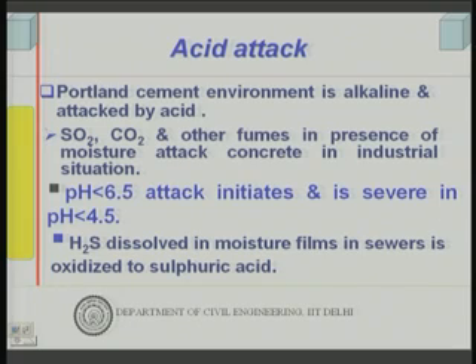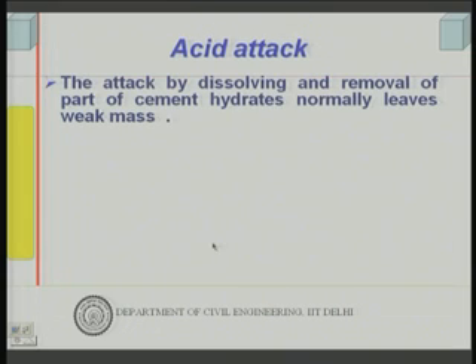One special case is H2S in the sewer lines. When it is dissolved in moisture films in sewers and then oxidized, it forms sulfuric acid. So, in sewers, at the point where the water level goes from low to high, you can have attack again due to sulfuric acid, which forms due to dissolution of H2S in the moisture film and then further oxidation of the product. This attacks, what does it do? It dissolves and removes part of the cement hydrates, normally leaving a weak mass.